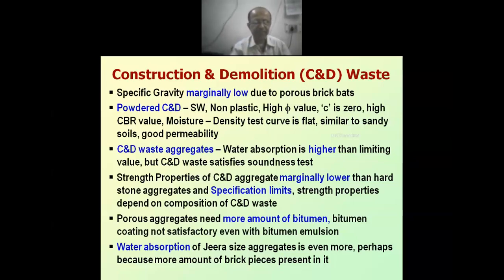The water will be acidic because of acid rain, and natural rain is also a little bit acidic in nature. So that's why we conduct the soundness test. It's a kind of accelerated weathering test. But these brick bats, whatever the CND waste aggregates are there, they satisfy the soundness test. That's a good point. Strength properties of CND aggregates are marginally lower than the hard stone aggregate. Strength properties in terms maybe of impact value, crushing strength, or abrasion strength. It's a little bit lower compared to natural mineral aggregate, and lesser than the specification limits.